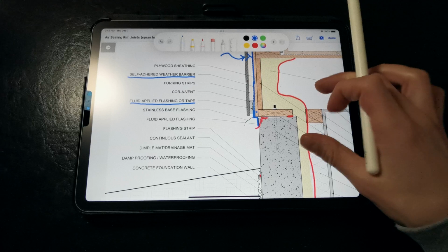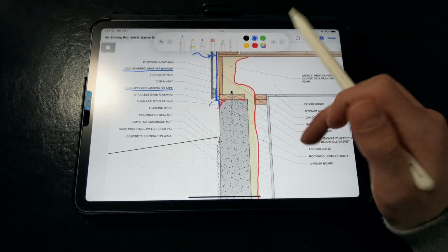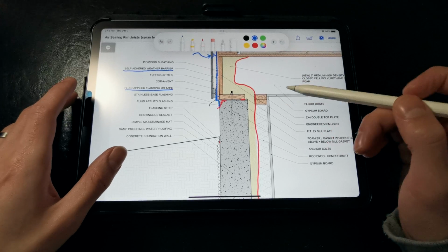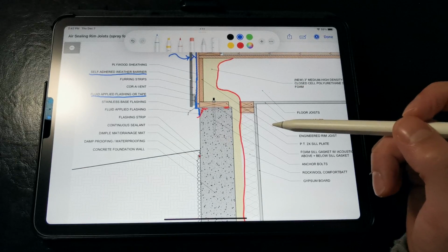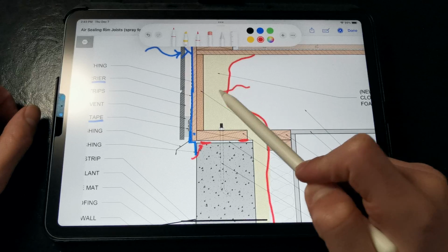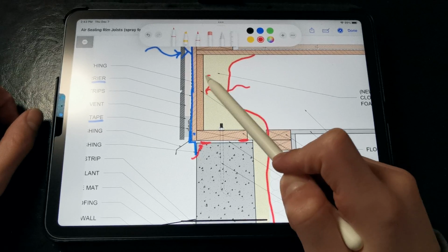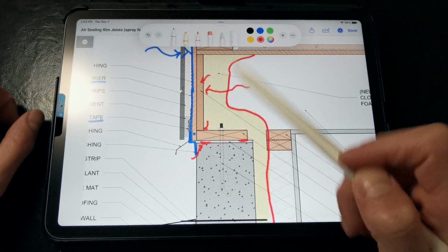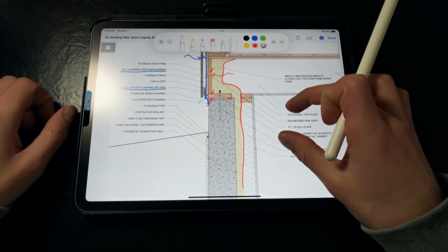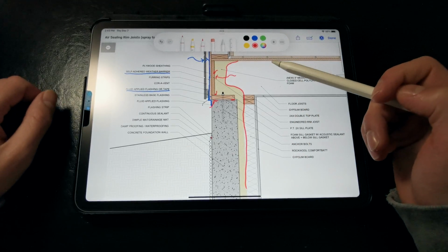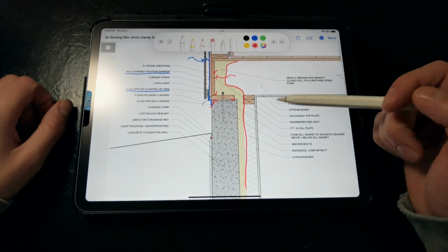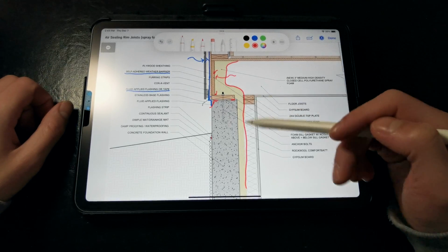Now, one thing you need to be aware of with spray foam, we're learning some pretty nasty things about spray foam. We know that rapid expansion and contraction of the wood framing can cause spray foam to crack because closed cell foam is rigid, and if that occurs, this essentially violates the integrity of the air barrier, and if moisture is deposited back here through air leakage, it's going to have a harder time drying out, and it could support rot, especially in those colder climates where we have a condensation risk. We're also learning that it off-gasses some pretty nasty chemicals, even long after it's installed, so we want to make sure that we're being very careful about using spray foam as an air seal, and even consider moving away from it.